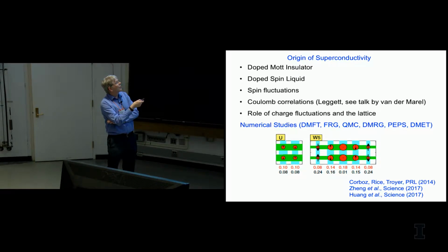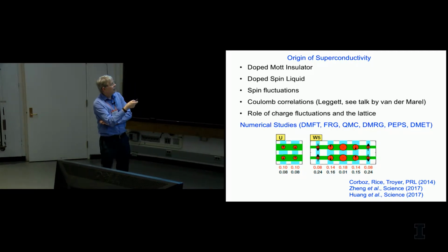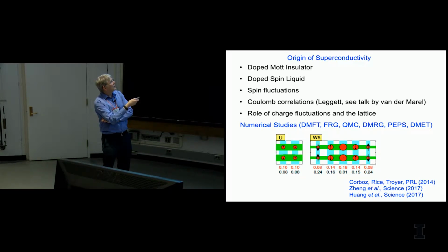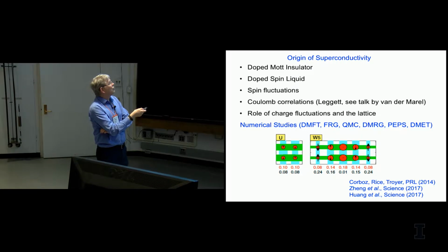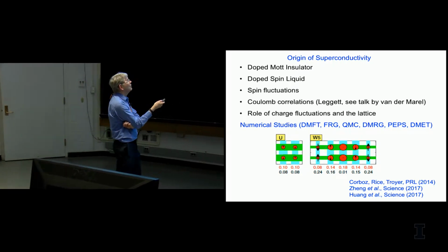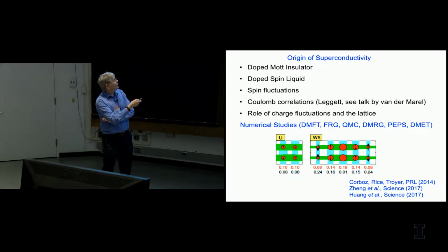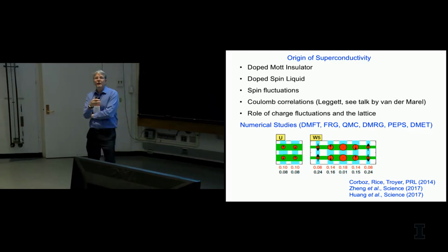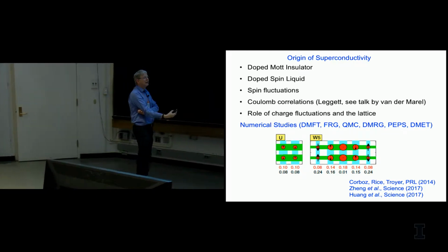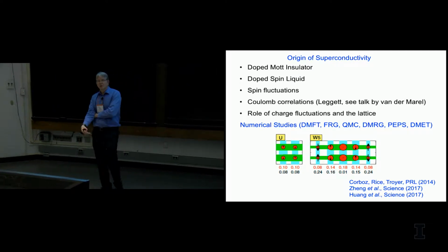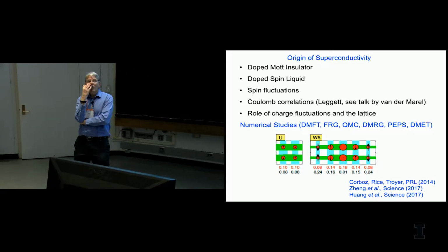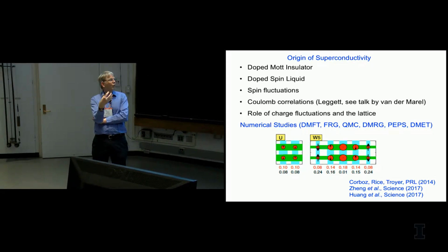Techniques like density matrix renormalization group, dynamical mean field theory, functional renormalization group, quantum Monte Carlo. PEPS and DMET are basically based on quantum information theory. And these studies all say pretty much a dramatic, interesting thing, that if you look at the doped Hubbard model, typically you will get modulated spins, modulated charge, and modulated pairing order parameter. So basically you get a PDW state which mostly also has charge and spin modulations present. And all these states are very comparable in free energy. So small changes in the theory can stabilize the superconducting state, it can stabilize a pair density wave state, it can stabilize a CDW state, or it stabilizes an SDW state. And this is what makes this problem very hard, that for strong correlations you have many states with comparable free energies that compete with one another.